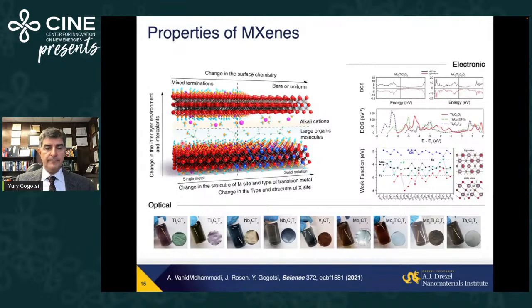But moreover, again, unlike in graphene or molybdenum sulfide that's very difficult to functionalize, we can covalently or by electrostatic attraction to negatively charged MXene surfaces bind functional groups, organic molecules, ions, basically graft molecules, or attract ions. Or we can intercalate multi-layer structures to further tune properties of the materials.